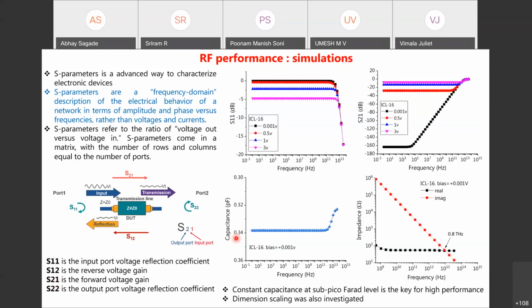I have simulated these devices before fabrication and measurements and obtained the S parameters. I have not shown all the parameters here; I am going to focus only on S11, which is a reflection parameter, and the second one, S21, which is a transmission parameter. What you can look at here is that S11 is almost stable and flat. Please ignore the various colors because these are at different voltages. Only look at the smallest voltage, close to 0 volt, which is the black line.